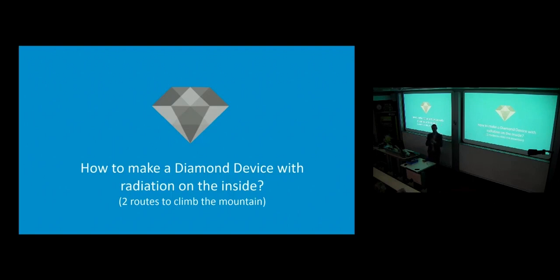And we call it a beta voltaic because we use beta emitting radioisotopes to provide the energy to drive the voltaic. So I talked about a sandwich before. This is a different flavor of sandwich. It's a sandwich where it's a continuous diamond structure, but it's isotopically layered. And in the center of that diamond we have a layer of radioactive carbon-14 containing diamond. And with every beta particle that's emitted, if you design it right, that 50 keV beta particle is converted into a shower of electrons. And the great thing about diamond is it doesn't get damaged because it's so strong.